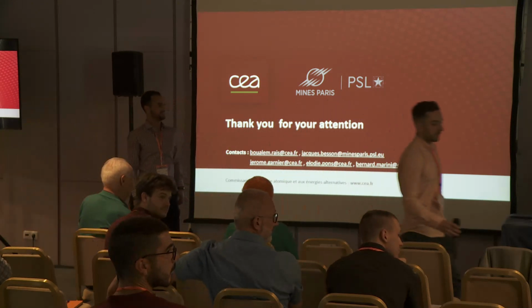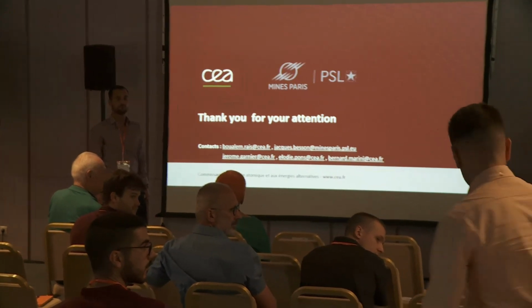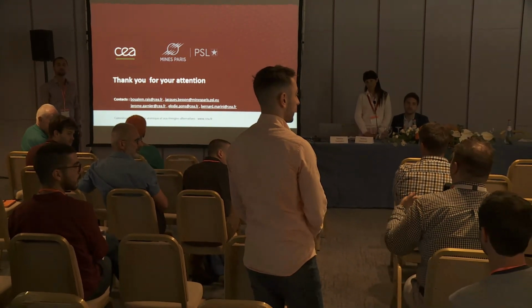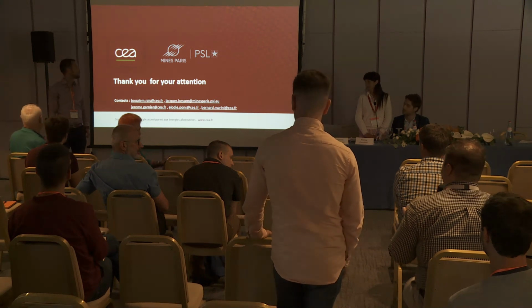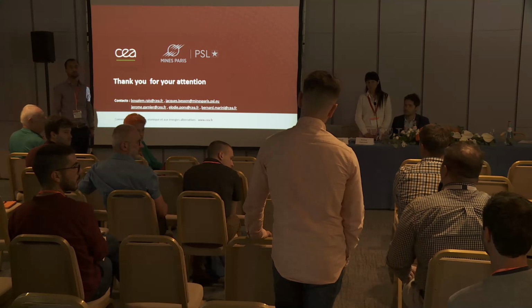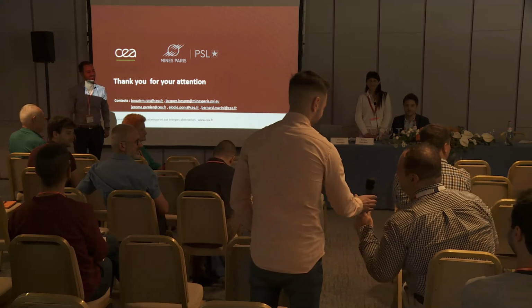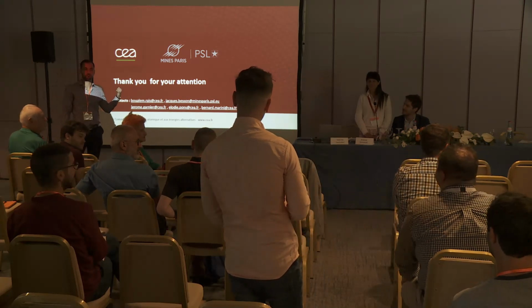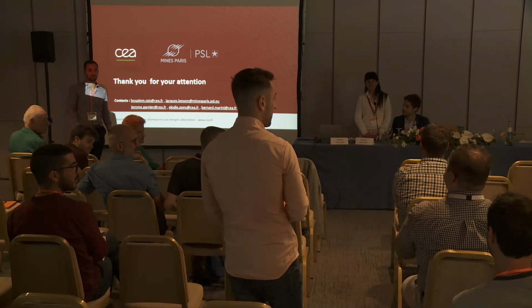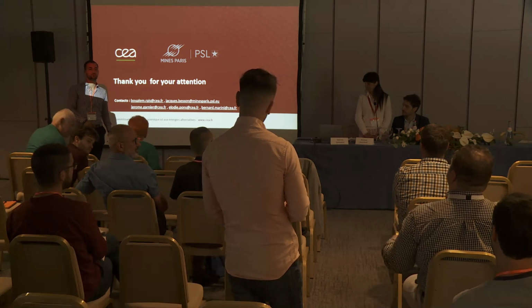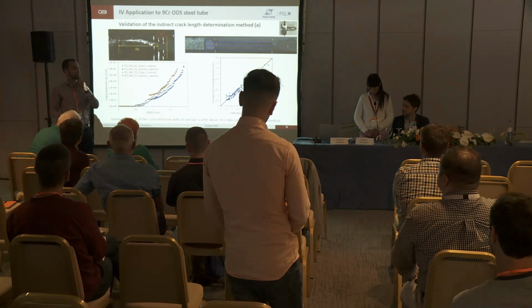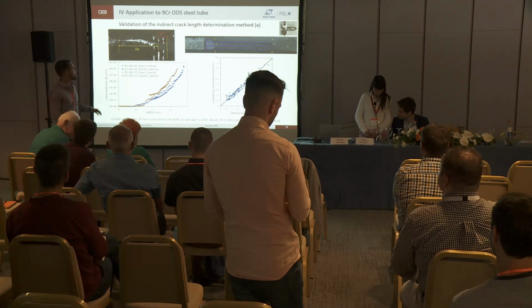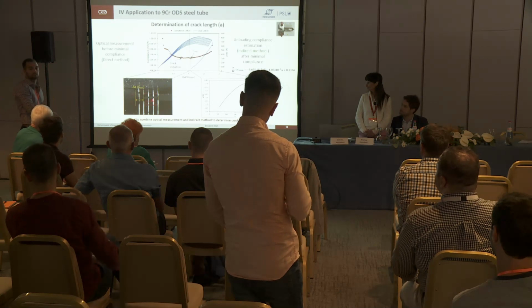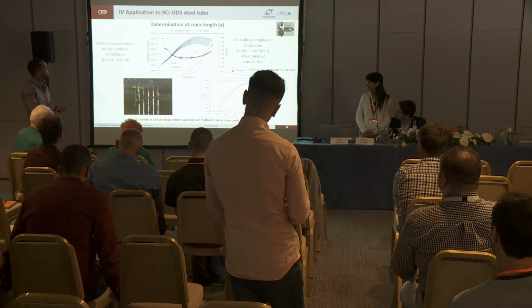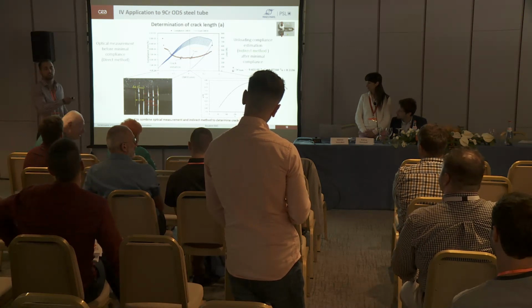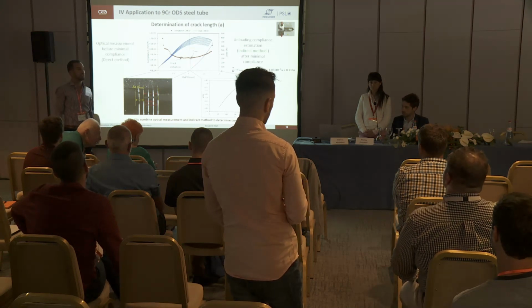Other questions? Okay. Thanks for your talk, of course. My question is, you used zircaloy as your material for the claddings in these, correct? It's an ODS steel. It's an oxide dispersion strengthened steel. Okay, good. If it's not zircaloy, I don't have the question. But it could be used for zircaloys. Oh, zircaloy is on the way out. That's the issue. I was thinking of maybe extending to APMT or those materials that are more accident tolerant fuel, more ductile than this ODS steel. So this phenomenon, the crack initiation, doesn't occur before our minimum compliance. So we can directly apply the indirect method. So that's the advantage with zircaloy if we apply this experimental method.